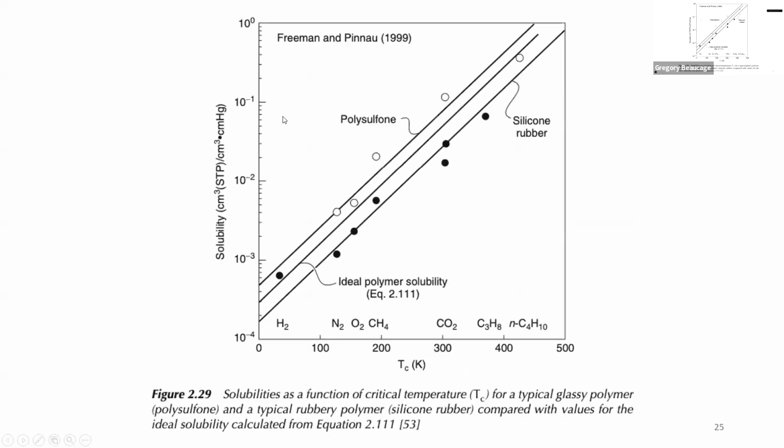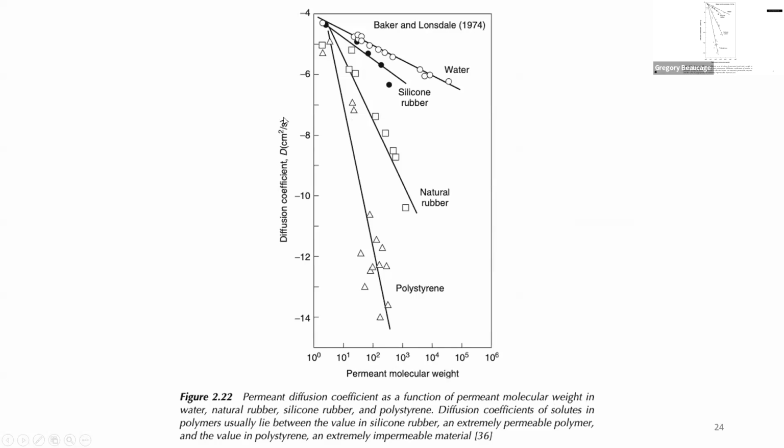And there's various trends, and so people have studied every possible trend. And these don't necessarily make that much sense. Like log of molecular weight and diffusion coefficient. So diffusion coefficient should go with 1 over the size, and the size should go as molecular weight to the 1/2, right? If it's a polymer thing. And then that means molecular weight to the -1/2.